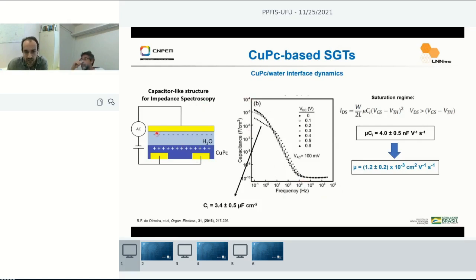We see that when the electric field oscillates at very low frequencies, it oscillates very slowly, so we have enough time to achieve polarization and form the electrical double layers. So what we expect is a plateau here for the capacitance of the electrical double layer. What we saw for this device was that we don't reach a plateau, although we observed values that agree with the theory for the electrical double layer, around 3 microfarads per square centimeter.